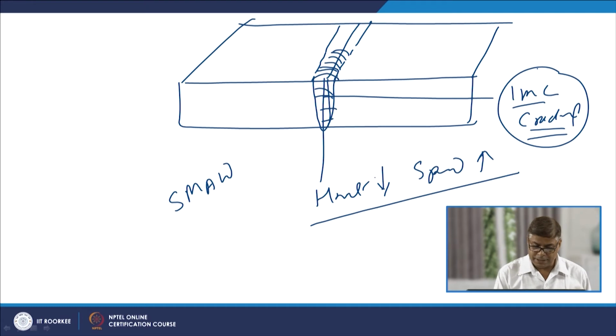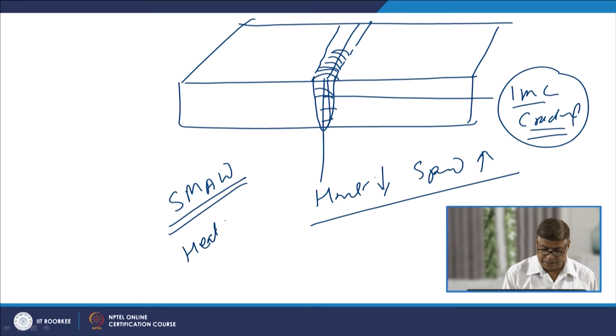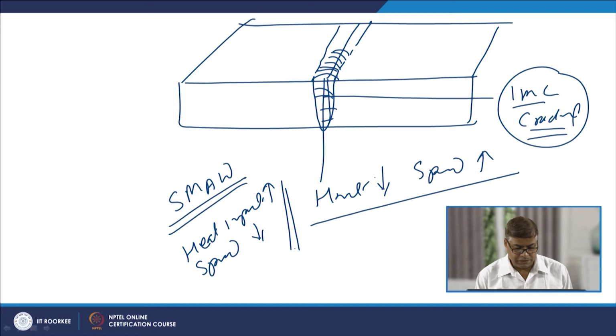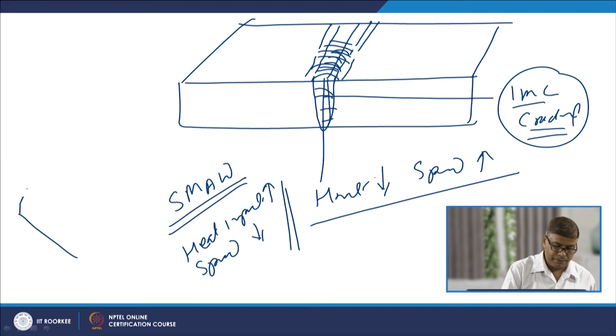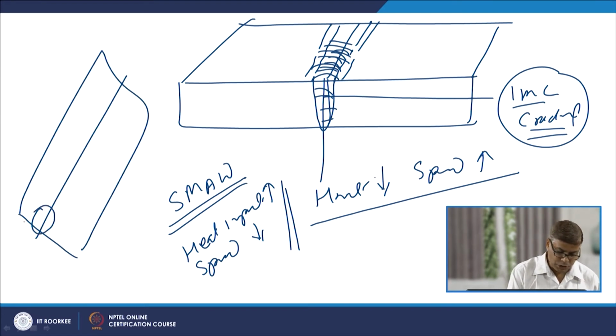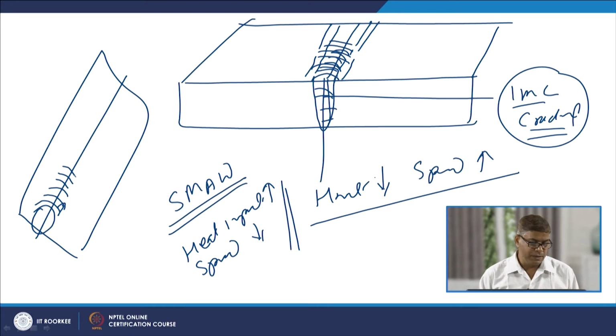As compared to this, in case of the SMAW welding, heat input is more and the welding speed is less. The combination of higher heat input and lower welding speed leads to effective melting and evaporation of the zinc during the welding. So, like this is the plate, this is the line of the weld, and this is the source of the heat, that is the arc. Since the arc is moving slowly, the zinc which is present ahead of the weld center line will be melting and evaporating. So, most of the zinc will be evaporated instead of getting into the weld pool.